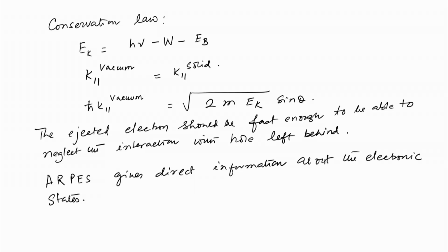Okay. So, that is the way that one can understand that the gap function of these Cooper pairs has a structure and is not uniform in K space. It has some nodal points from which electrons can be excited, and that can be detected via angular resolved photo emission spectroscopy, and this has indeed confirmed the presence of a D wave gap in certain unconventional superconductors.